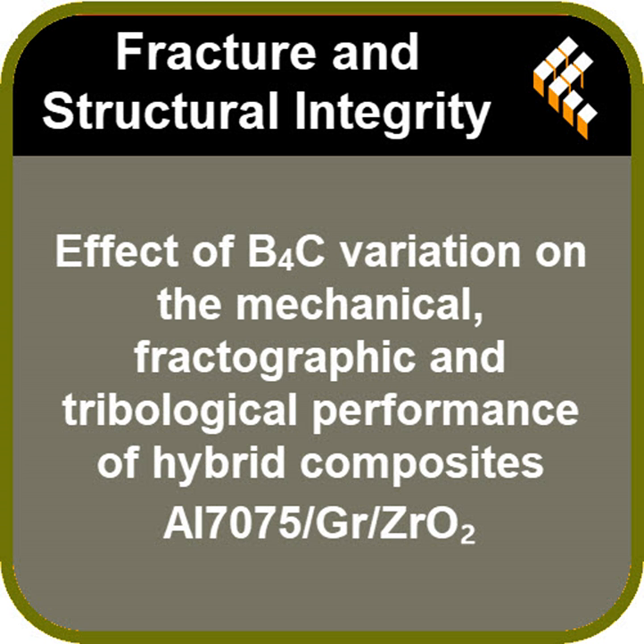Okay, so we've accepted a slight loss in flexibility for a massive gain in strength. But what about long-term durability? How did it hold up under constant friction? The wear results were phenomenal. They used standard pin-on-disc testing. At the highest applied load, 40 newtons, the 4% B4C composite showed a 34.8% decrease in wear loss compared to the base alloy. That's incredible.